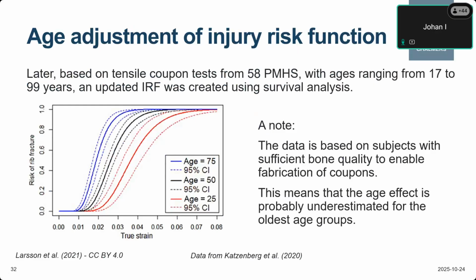A note about this data is that it is based on subjects with sufficient bone quality to enable fabrication of coupons. I know that when they did this, they had some coupons that broke before they could test them. They were too fragile to handle. So this means that the age effect is probably underestimated for the oldest age group, because it was basically very hard to create coupons from some of these subjects.